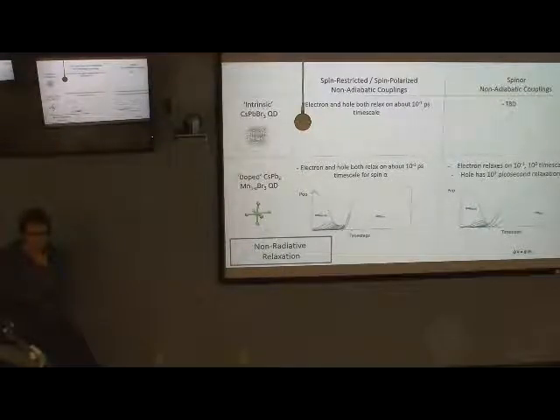So you can get spin flips for non-radiative? Yes. If you are in the basis of spinors, you're allowed to. Actually, it can be not really slow. That is a reason why you may want to track the magnetization as a function of time. So if there are no spin flips, then overall magnetization will stay constant, but if you have spin flips, it may change.